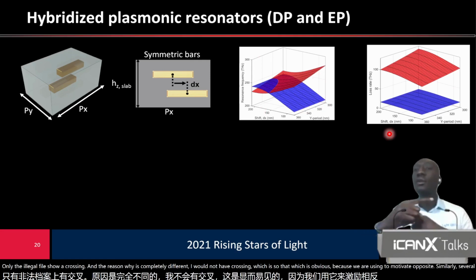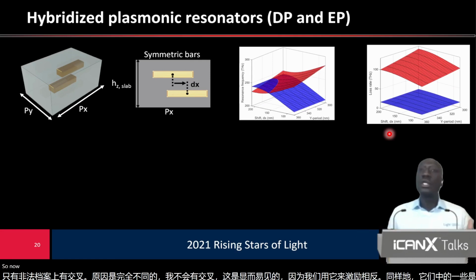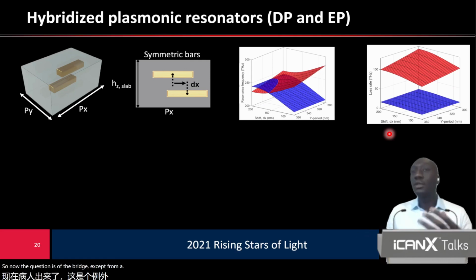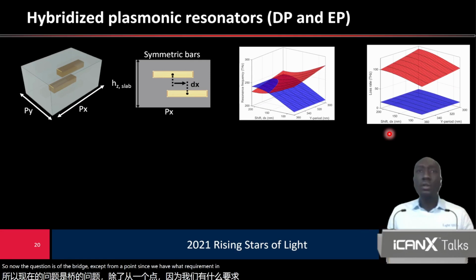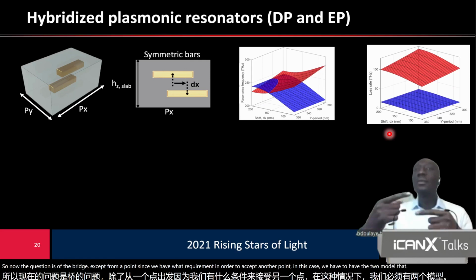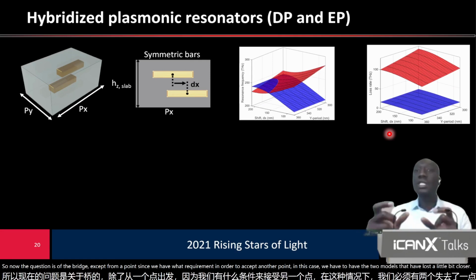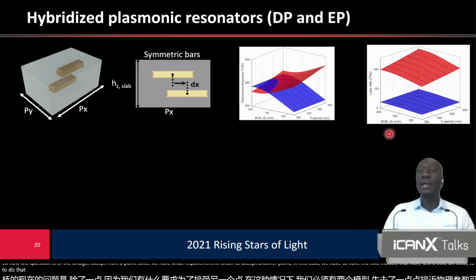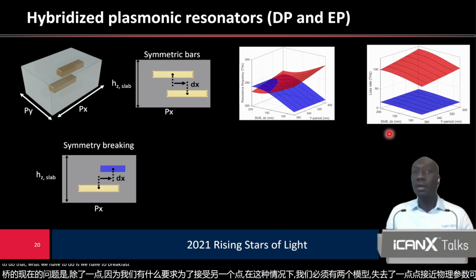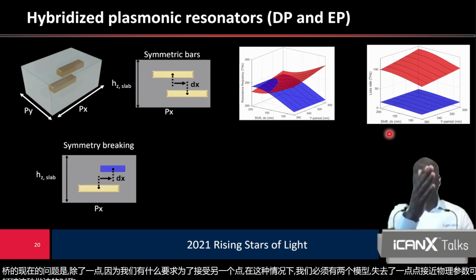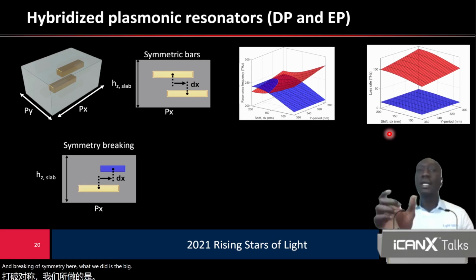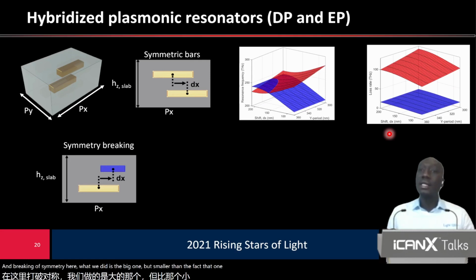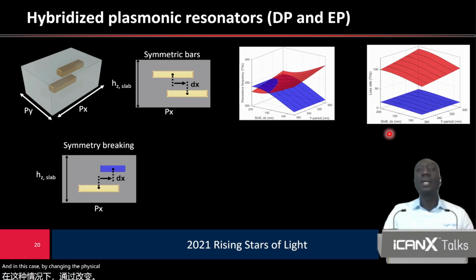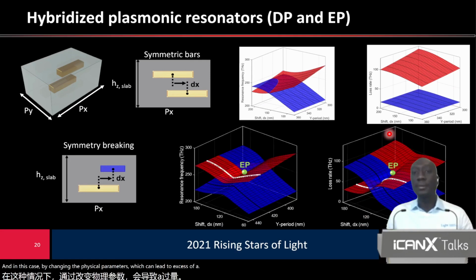Their loss rates are completely different. So now the question is how to reach the exceptional point, since we have all the requirements. In order to reach the exceptional point, in this case, we have to have the two modes that have loss a little bit close, so that physical parameters can make them exactly the same. To do that, we have to break the symmetry of the structure. And breaking the symmetry here, what we did is we take one bar smaller than the second one. And in this case, by changing the physical parameters, we can reach the exceptional point.